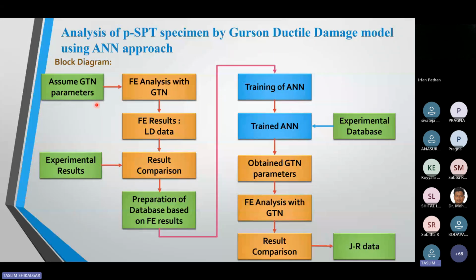I performed almost 100 simulations to get the load displacement data with this type of damage mechanics model. Here I compared all load displacement data with the experimental data I showed initially. This comparison is important because I want to make a range around the experimental data. So my experimental data will fall between the upper and lower limit of the FEA load displacement data. I observed that some data is below the experimental data and some data is above it.